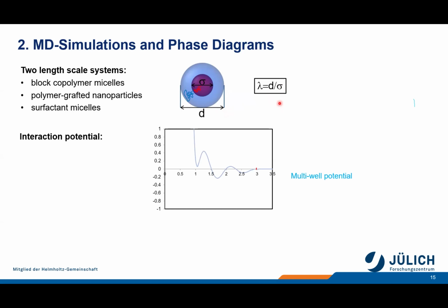We would then, for the simulation, need an interaction potential. To get quasicrystals, people usually use multi-well potentials, where they artificially design this multi-well potential to have maxima at the positions where you would have an FCC or BCC packing in order to destabilize this, and then end up with different other kinds of phases, which could be quasicrystals. In our case, this is clearly not an appropriate potential.